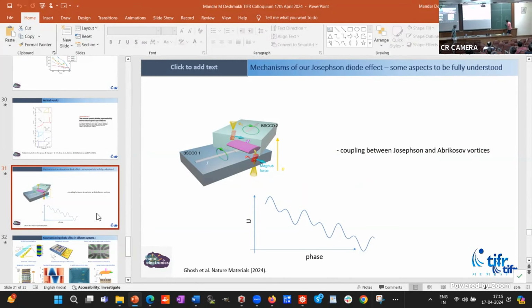So when you have a simple Josephson junction, as I told you earlier, the switching of the Josephson junction means that the more DC current you send through it, the more it tilts. And at some point, it can go by thermal activation, because it has to start sliding. Let's stick to thermal activation. If it slides, then you get a term which is phi dot, because the x-axis is phase. Now, one way to think about the asymmetry is if there is another harmonic, like a cos 2 phi kind of term, which is depicted here. If my system sticks here and I tilt it, the potential that I have to overcome for the system to escape on one side is different from if I tilt it on the other side. And that is the genesis of the non-reciprocal response.